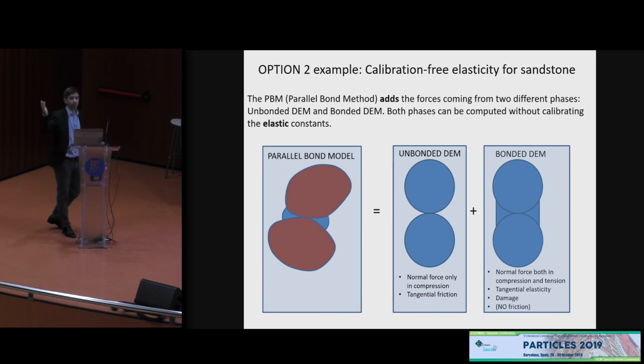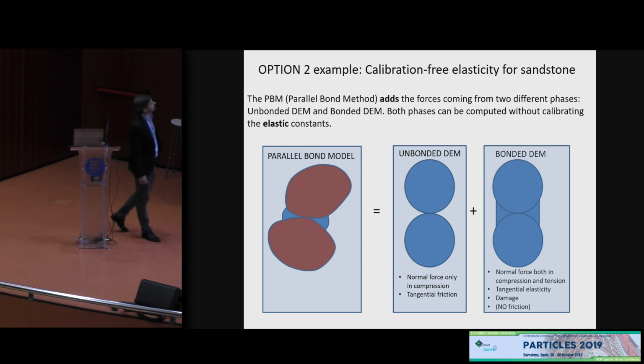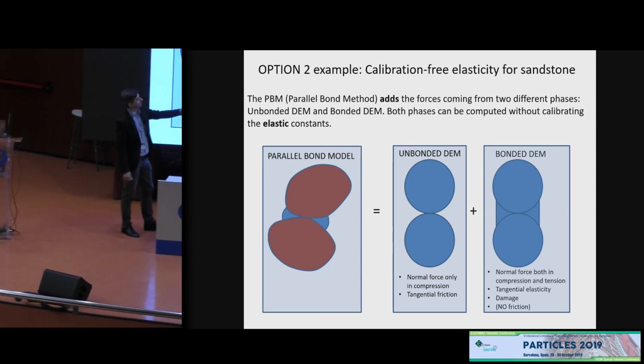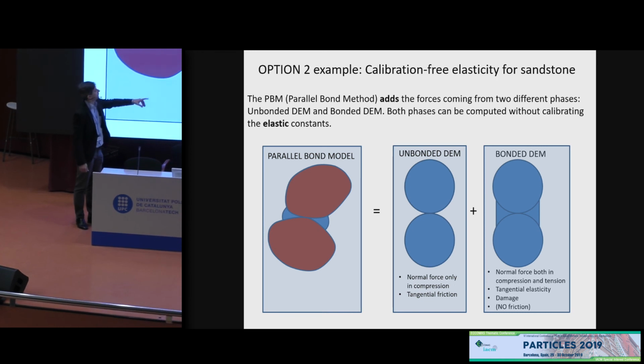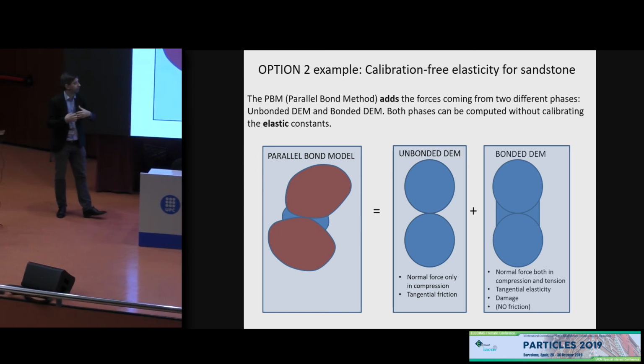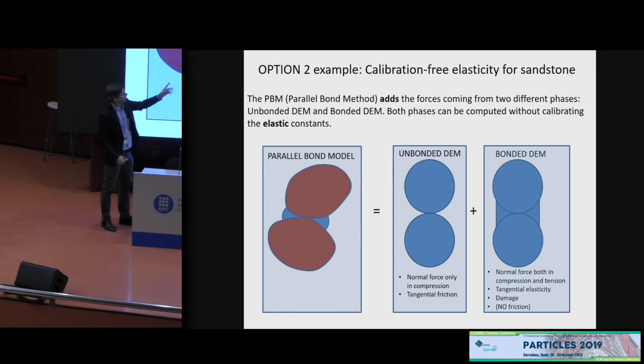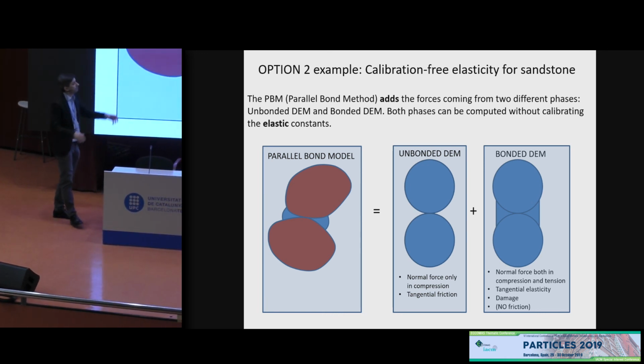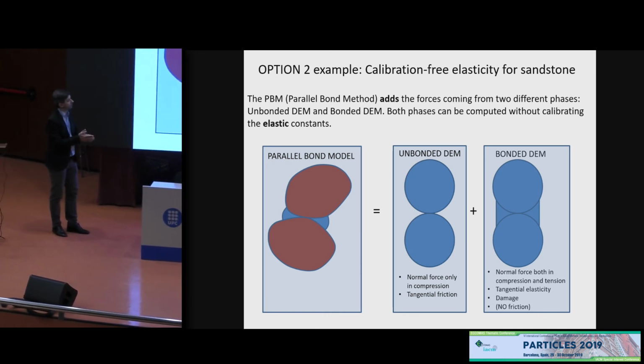For option 2, where the size of the spheres is the same as the actual grains, we developed the parallel bond method, which is a known method already. It's published and is also present in some commercial codes, which is based on parallel phases of DEM. On one hand, you have unbonded DEM, which is the skeleton. The grains are touching each other. And on the other hand, you have a bond on top of that, which makes them cementitious material.